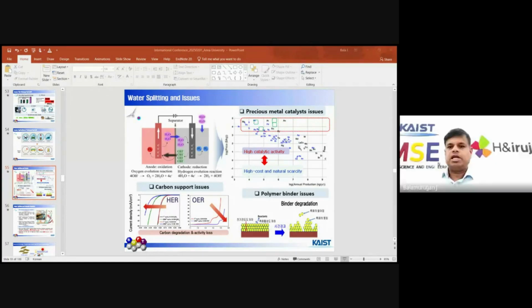So what do commercial companies using hydrogen fuels use in water splitting technology? Platinum carbon as the cathodic material, and iridium oxide or ruthenium oxide as the anodic material. But when we are using platinum carbon, the cost is very high. Even though the catalytic activity is very high, the cost is very high, and the natural scarcity and durability are one of the great challenges.